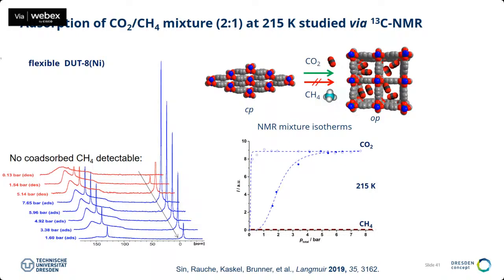And what is very characteristic for the NMR spectra, for static NMR spectra, is that when the molecule is mobile, here this is the methane signal, this is the CO2 gas phase signal. When the molecule is mobile, you get a very sharp peak. But once your molecule enters the pores, it is restricted in mobility. And in a static NMR experiment, then you get a very broad peak, which is called a tensorial signal. And this has a very characteristic signature for the adsorbed species. And this allows you to distinguish between the adsorbed species, which is this broad signal, and the mobile species in the gas phase.